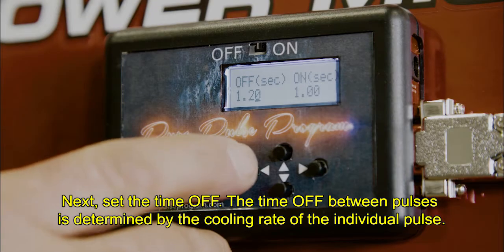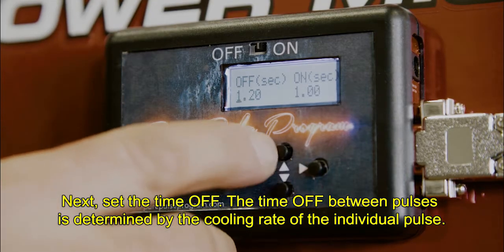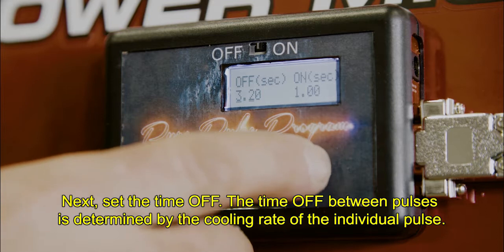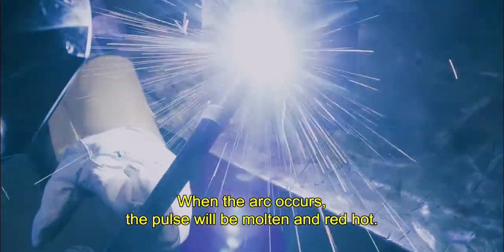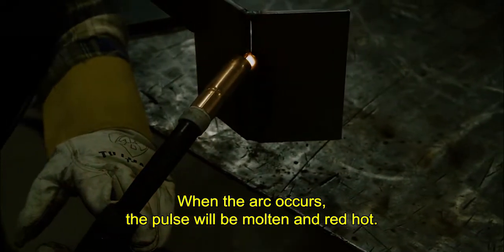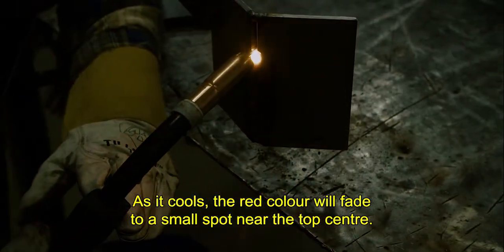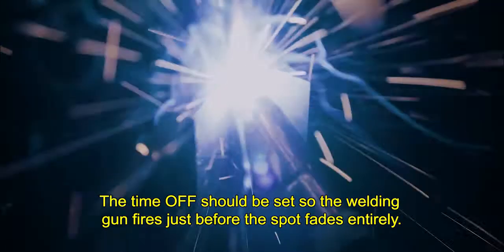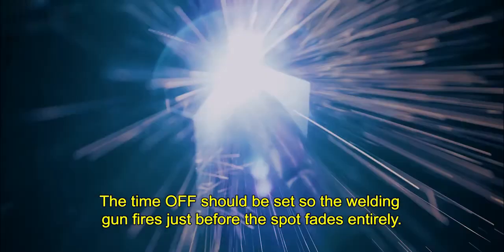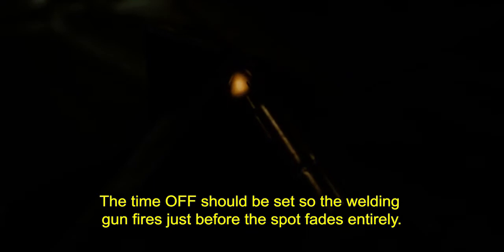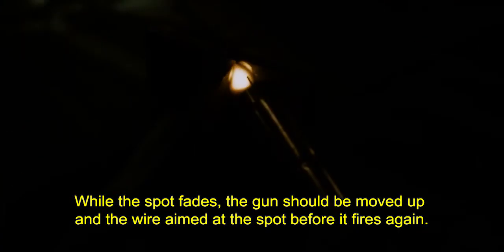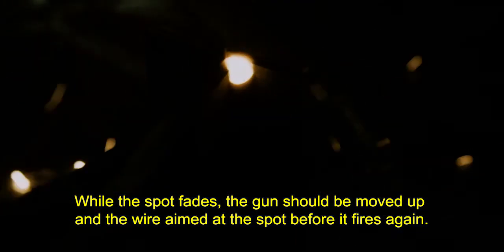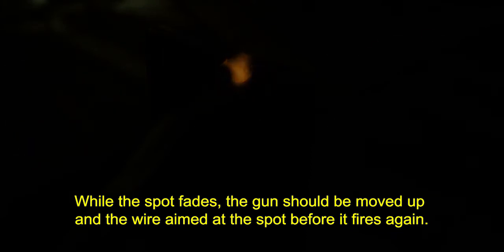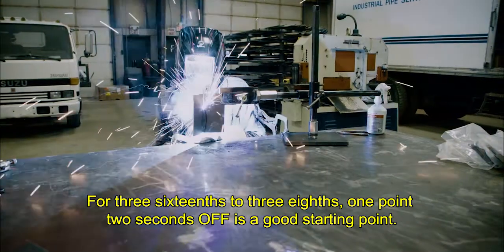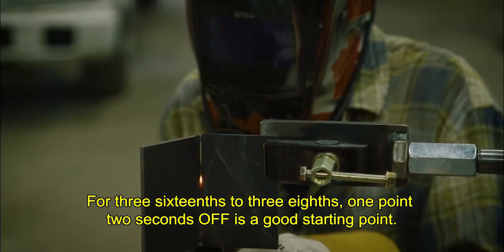Next, set the time off. The time off between pulses is determined by the cooling rate of the individual pulse. When the arc occurs, the pulse will be molten and red hot. As it cools, the red color will fade to a small spot near the top center. The time off should be set so the welding gun fires just before the spot fades entirely. While the spot fades, the gun should be moved up and the wire aimed at the spot before it fires again. For 3/16 to 3/8, 1.2 seconds off is a good starting point.